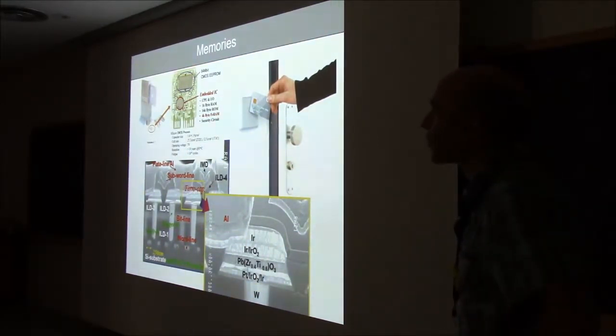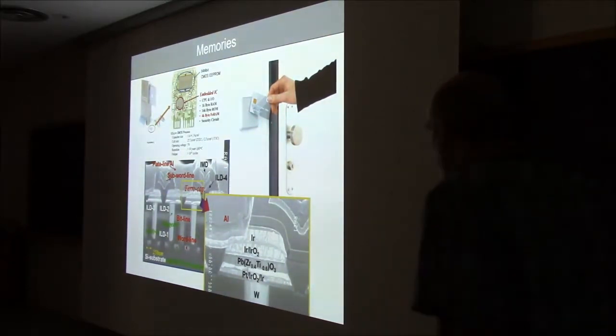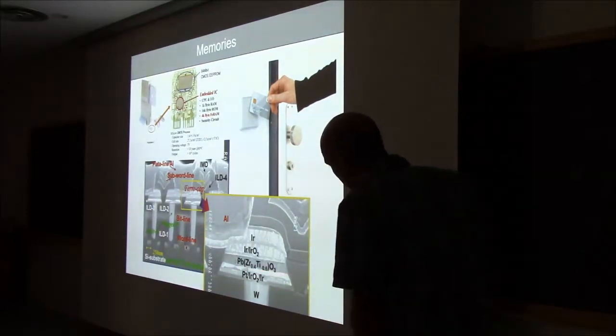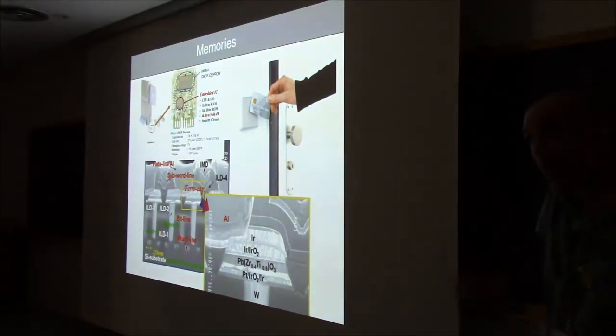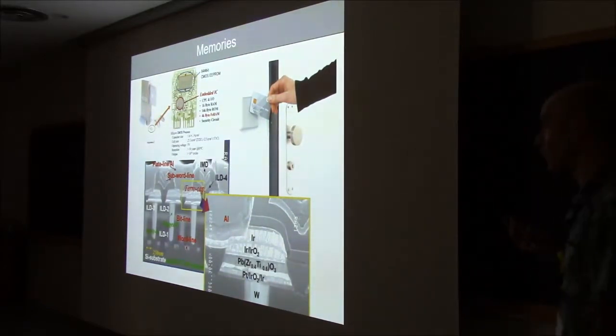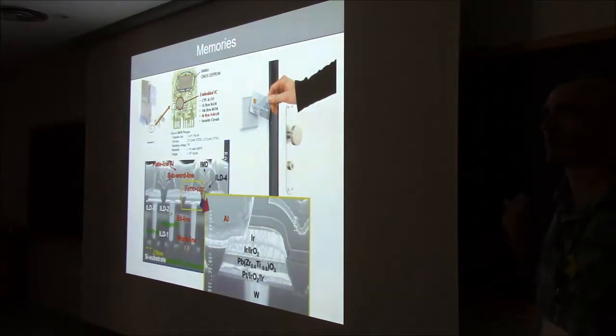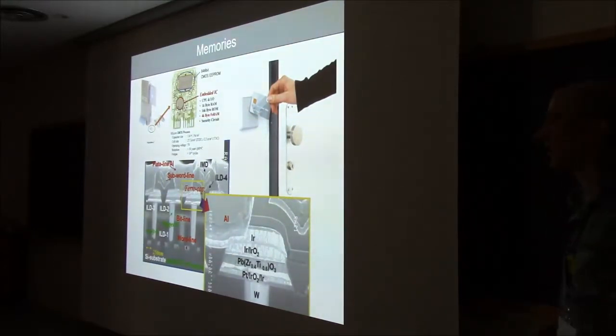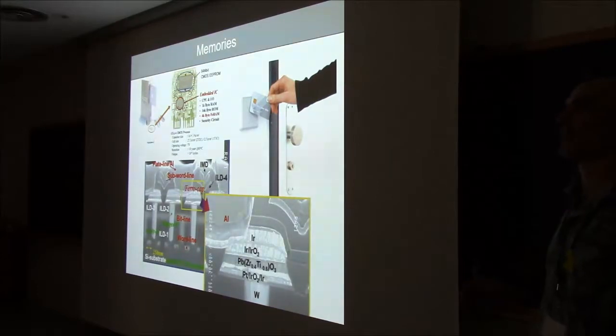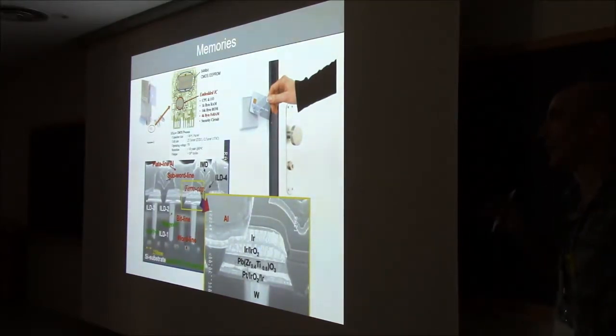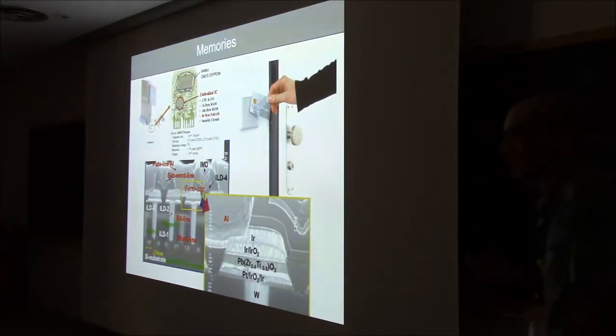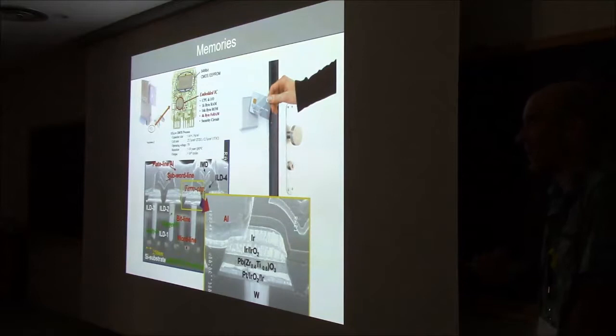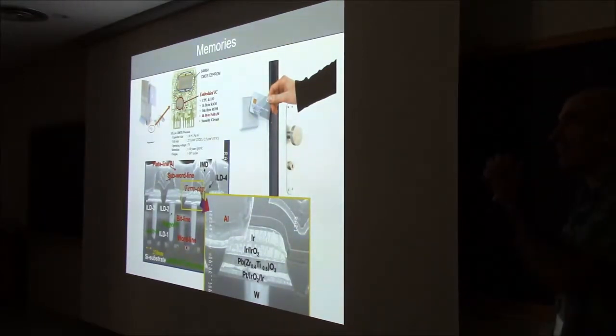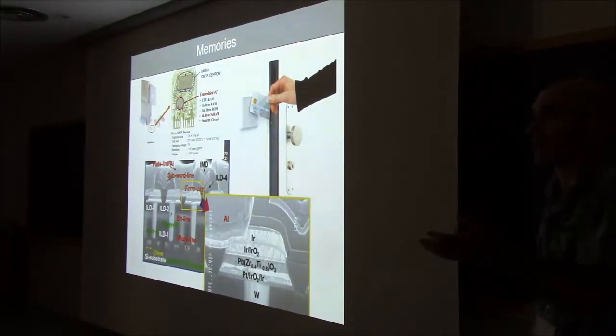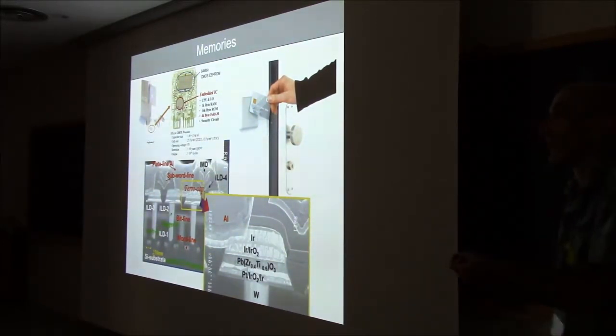Nanometers. I don't know. I can tell you some of the physical limitations that you're going to encounter when you go small. One of them is that if you go too thin, you can have leakage currents or tunneling currents or shorts of many kinds. You also will have depolarizing field effects, and if I have time, I will talk about depolarization, which destabilizes your polarization, makes it less stable. Now, the critical thickness at which that happens depends a lot on the quality of your film. So I can give you a figure, but it would be meaningless. But basically, in my lab, I've never been able to measure a stable hysteresis loop in anything thinner than 10 nanometers. Now with a PFM you can go smaller, you can probably go to 5, but in practical terms...